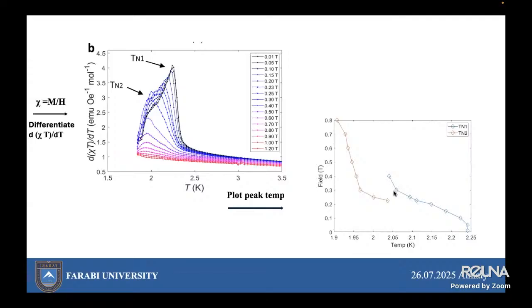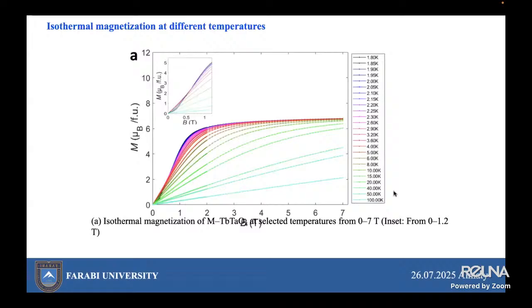And after that, we researched the isothermal magnetization at different selected temperatures, as shown in this figure. Below the higher Néel temperature, the isothermal magnetization exhibits a characteristic shape. The inset is a zoomed version of the region between 0 and 1 Tesla. Here, magnetization is in units of Bohr magnetons per formula unit, and B is the external magnetic field in Tesla.